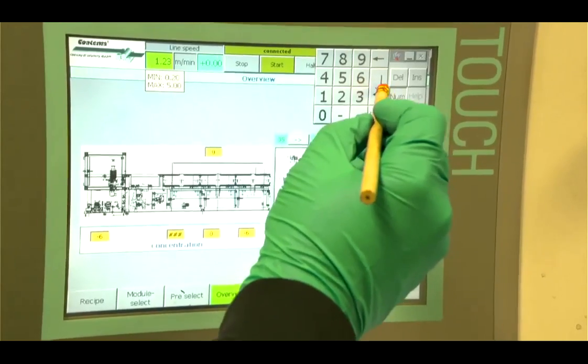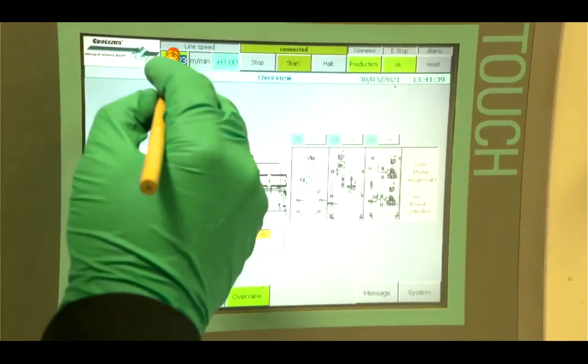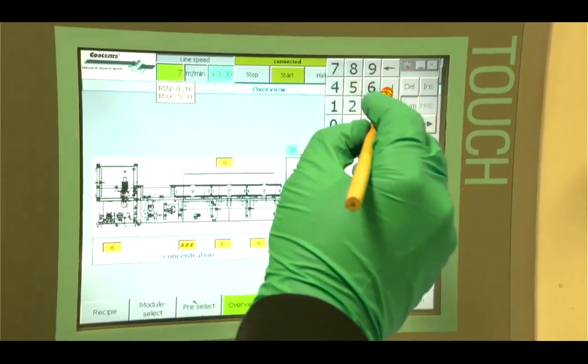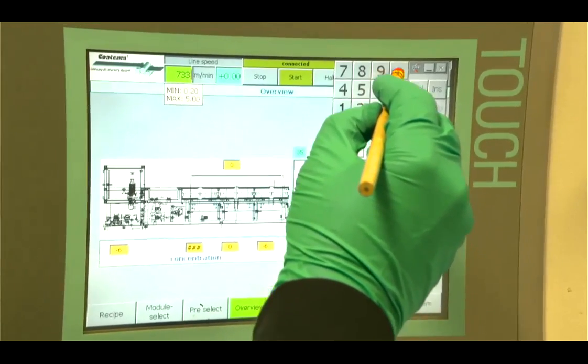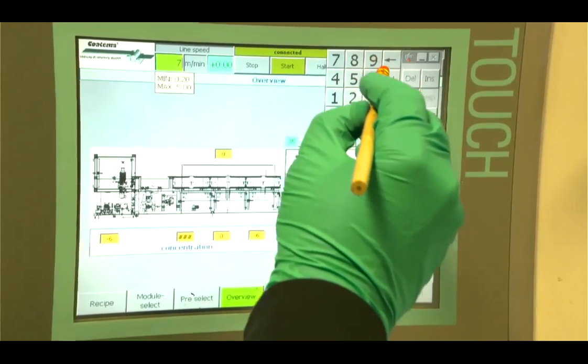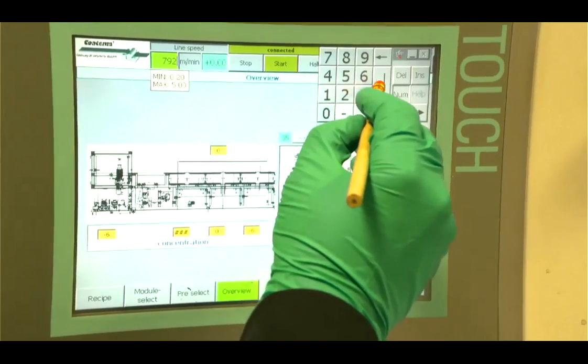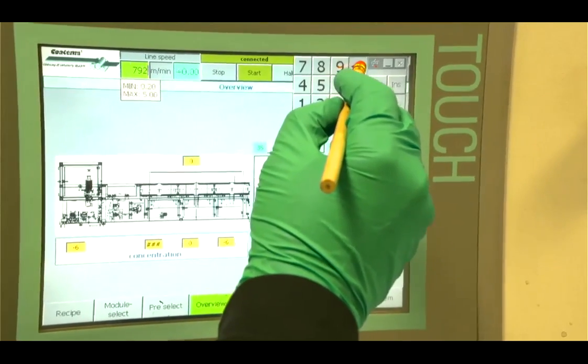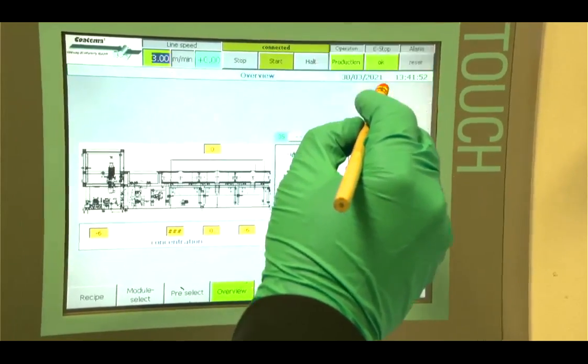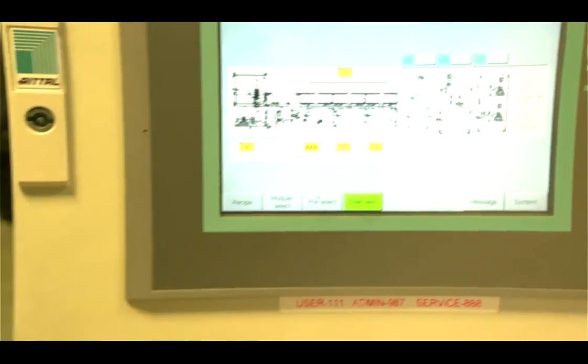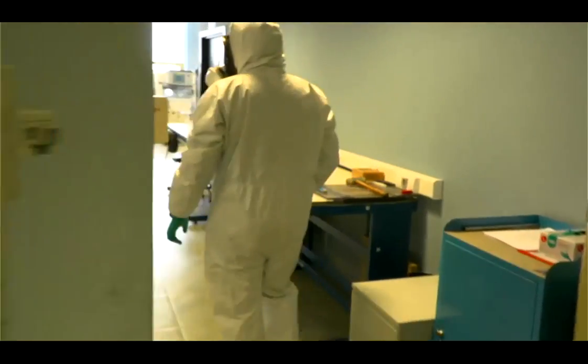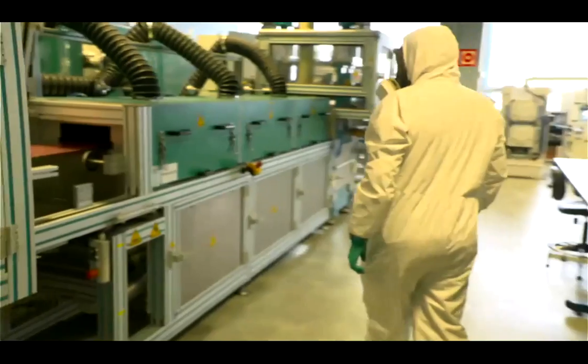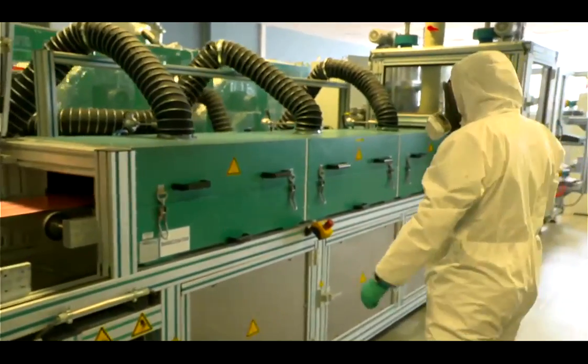So in these 3 meters, if we are coating at a speed of 1 meter per minute, that means that in 3 minutes the electrode has to be dry. So when we are producing thick electrodes, it's not possible to use 1 meter per minute, because there is no time to dry the electrodes.